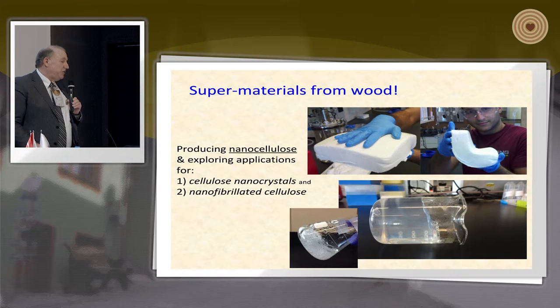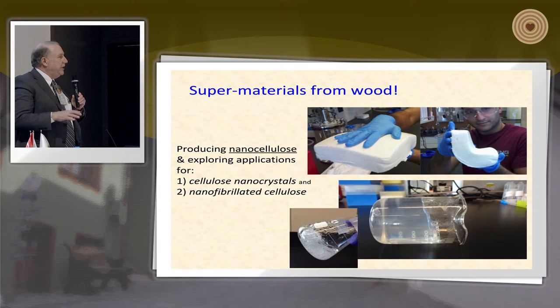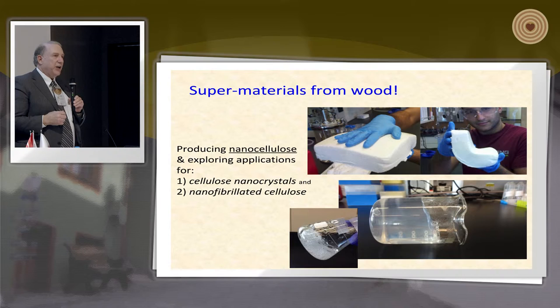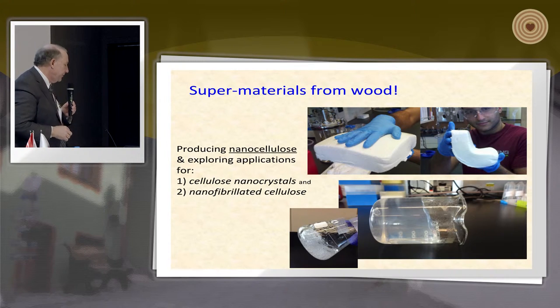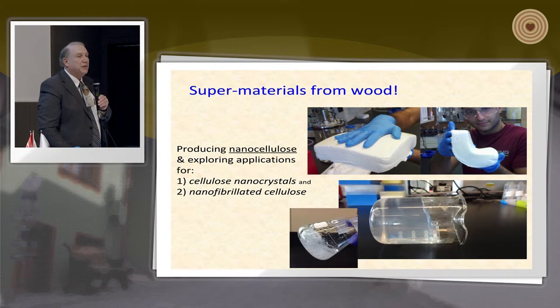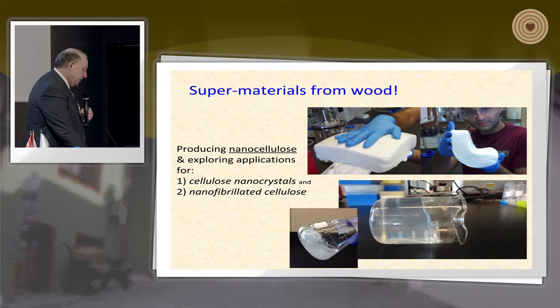The last thing I want to cover is these super materials from wood, and hopefully the samples I've passed around have been seen by most of you. We're producing nanocellulose in our lab. One way to produce nanocellulose is to start with bleached wood pulp and run it through a nanohomogenizer — a large pump that forces the pulp through fine nozzles in a shearing process. What you end up with is a clear gel — that's the material in the little baggie that says 'please do not open.' You can squish it around with your fingers, but don't open the bag.